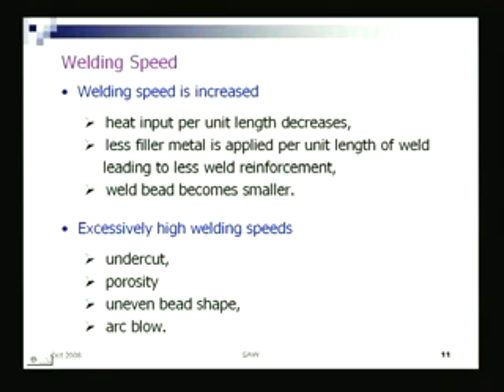As I move the heat source faster, the cooling effect is faster. The molten metal will get solidified before the gases can float out, so this may lead to porosity.